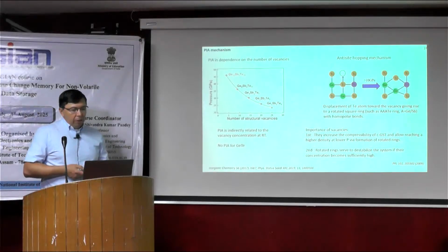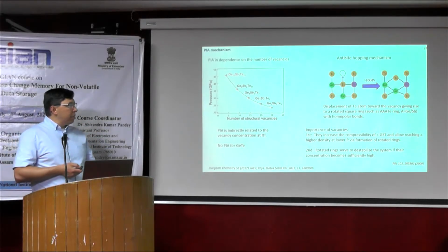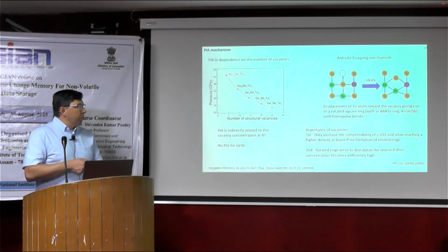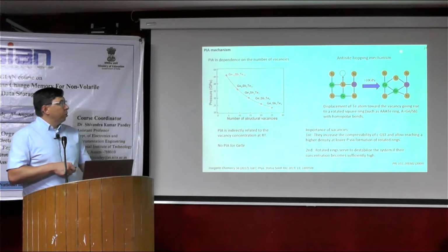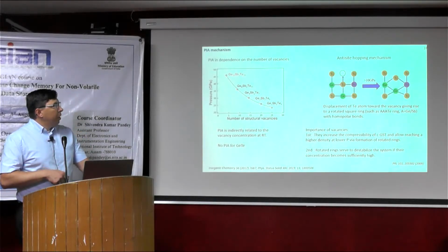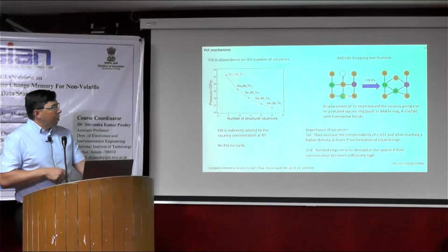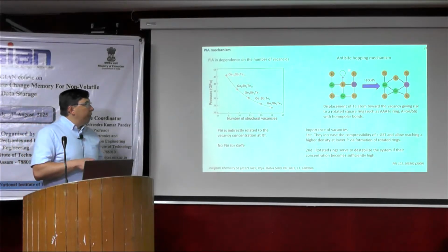For this amorphization process, a model called the anti-site hopping mechanism was proposed. If we consider our structure, like the cubic structure here, it consists of germanium, tellurium, germanium, germanium, tellurium. This is the cubic FCC. And then we have here a vacancy.